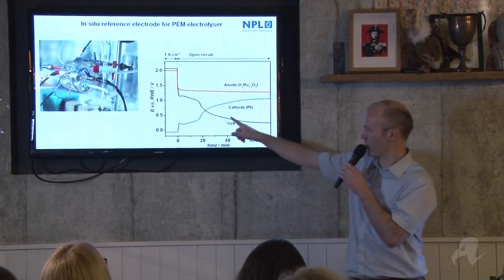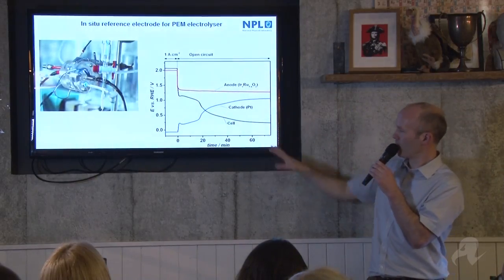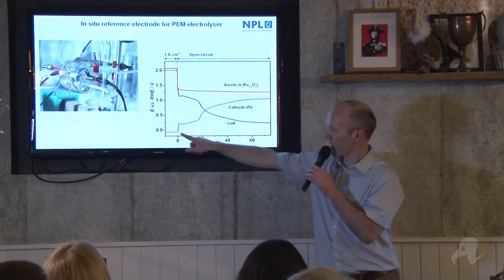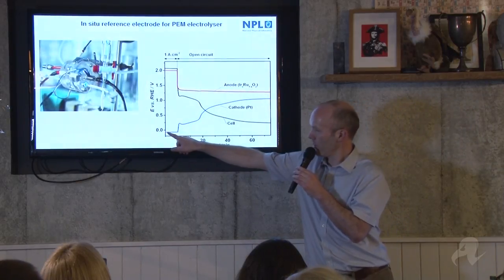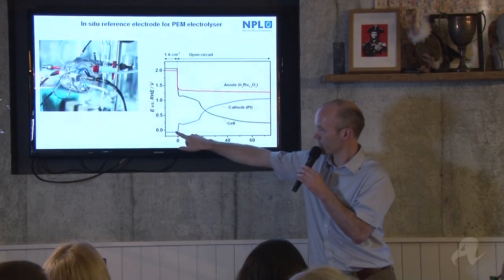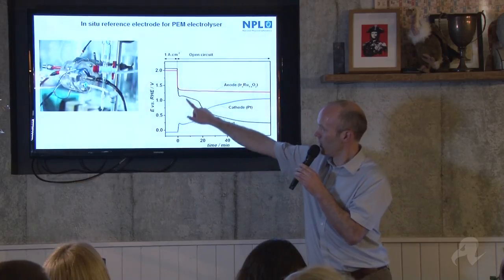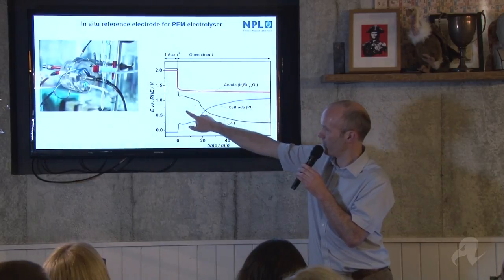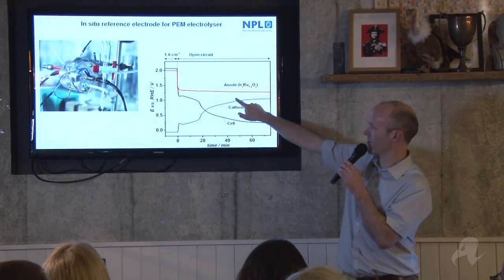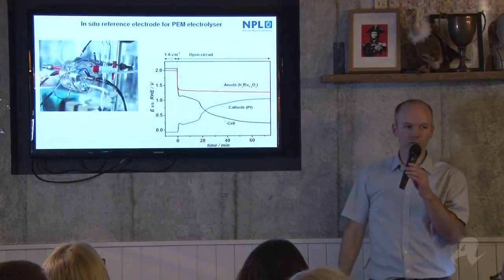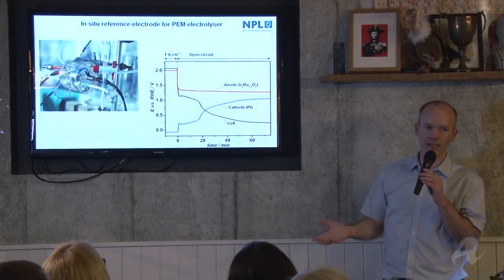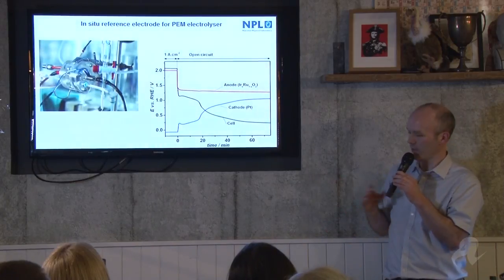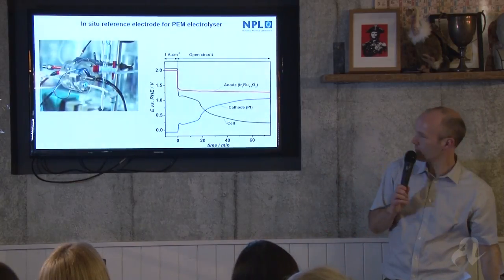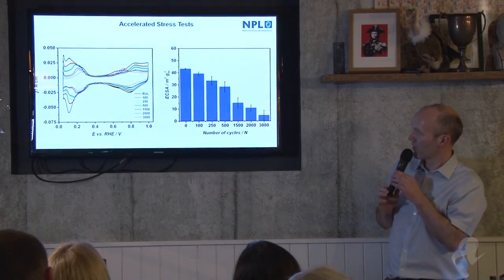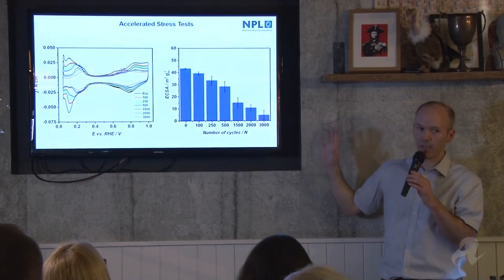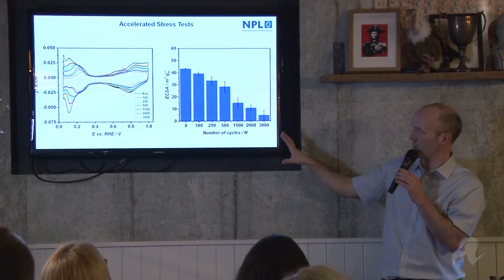between them, to drop. And what we showed in this work was, when you're generating hydrogen here, when you switch it off, oxygen from the anode is actually diffusing across and raising the potential of the cathode. And we knew from our fuel cell research that that leads to degradation of the platinum cathode. And that's what we saw. So this allowed us to then say to them, we need better materials for our anodes and cathodes.